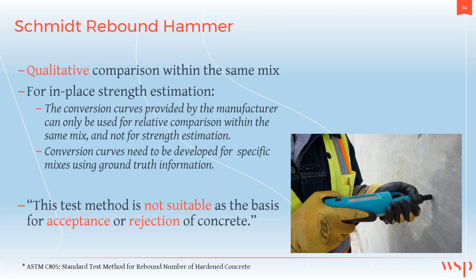Another somewhat more rudimentary technique that's been around for a long time is called the rebound hammer, also the Schmidt hammer or Swiss hammer. Its principle is to impart a pulse, essentially a spring-loaded weight of known mass and velocity, impacting the surface of concrete. The response of the concrete causes that mass to essentially rebound from the impact, and the degree to which it rebounds is indicative of the relative stiffness and hardness of the concrete.